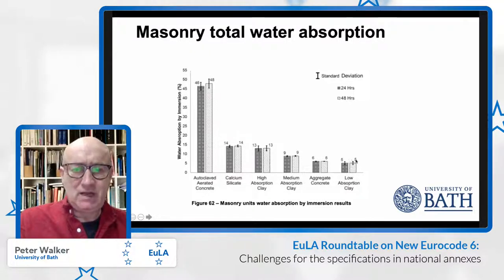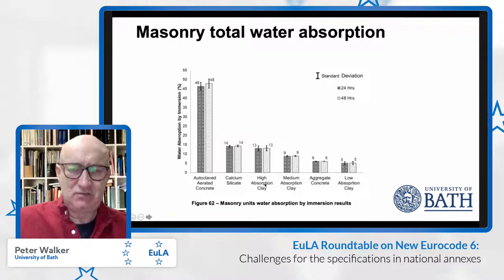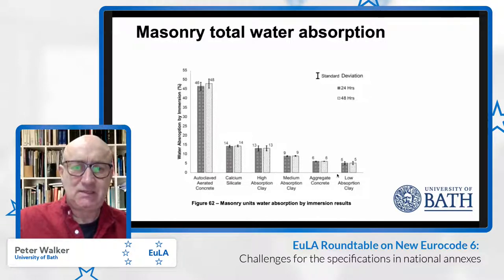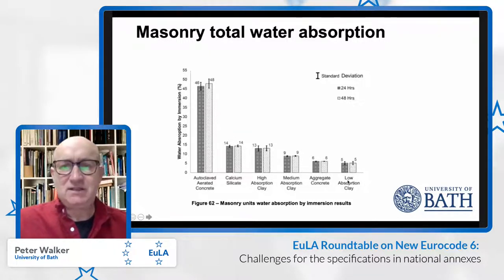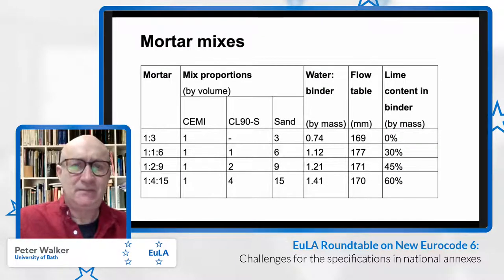We struggled in some ways to get a higher absorption. So we've called it high absorption, but 13% is not particularly a high water absorption unit. And of course, units with water absorption properties of 20, 25% for a clay brick is not unknown, but actually sourcing these in the current market proved problematic, and maybe a historic unit, if we'd got a recycled brick or something, may have given us a higher water absorption value. So these terms high, medium and low are somewhat relative in the context of the study.